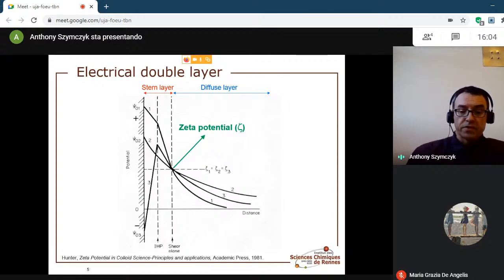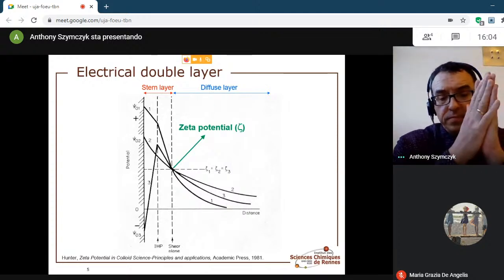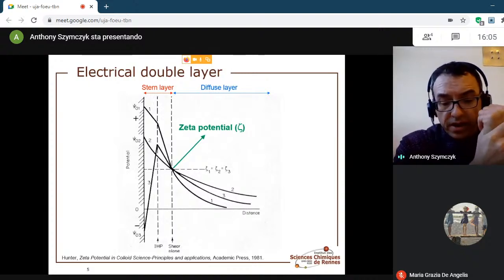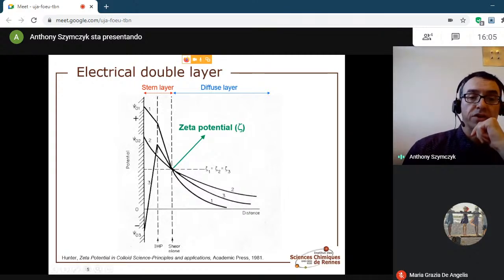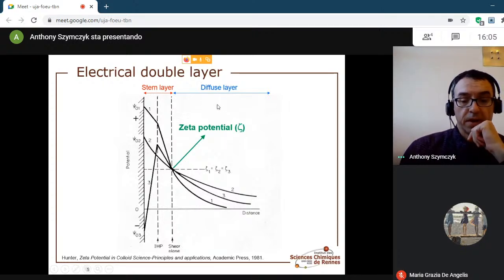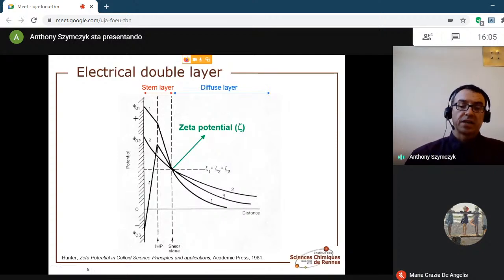The charged species at the membrane surface generates an electric field which propagates in the solution in contact with the membrane. Within the framework of the famous electrical double layer model, the zeta potential is defined as the value of the electrostatic potential at the hydrodynamic plane of shear between the Stern layer and the diffuse part of the electrical double layer. The zeta potential is a very sensitive indicator of the electrostatic interaction between a membrane and the surrounding liquid phase. Since it is intrinsically accounting for specifically adsorbed species, its determination proves to be very useful when investigating problems of practical relevance. And zeta potential is now part of the toolbox when it comes to characterizing membrane materials.